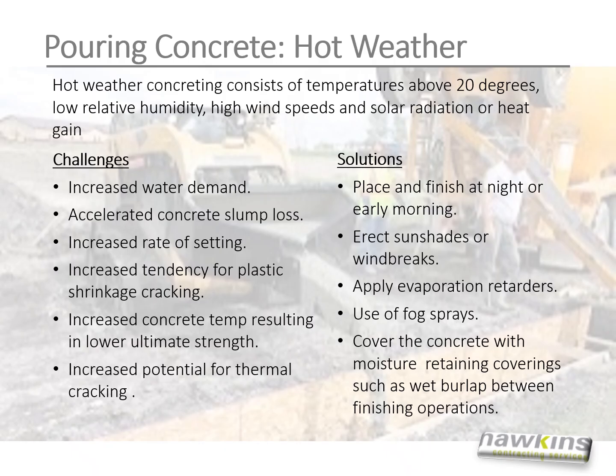Pouring concrete in hot weather. Hot weather concreting consists of temperatures above 20 degrees, low relative humidity, high wind speeds, and solar radiation or heat gain. The challenges: increased water demand, accelerated concrete slump loss, increased rate of setting, increased tendency for plastic shrinkage cracking, increased concrete temp resulting in lower ultimate strength, increased potential for thermal cracking. The solutions: place and finish at night or early morning.